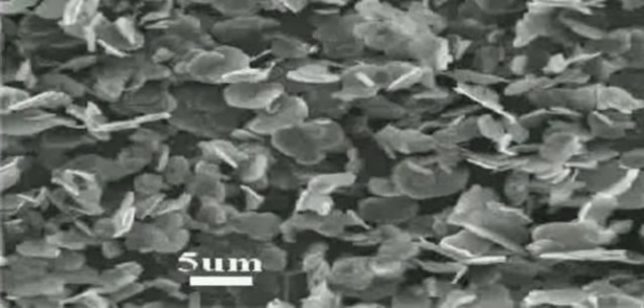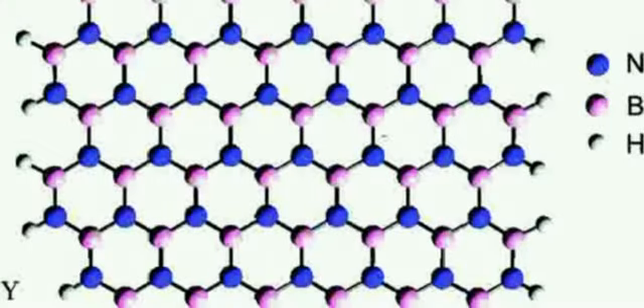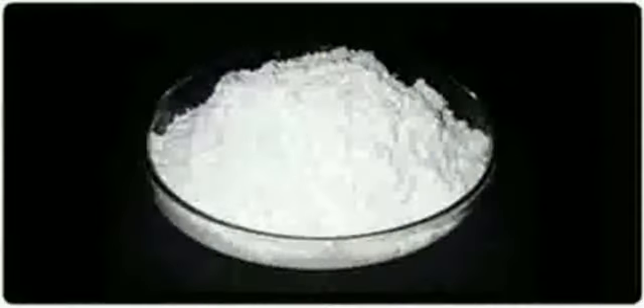Still, h-BN and graphite are very close neighbors, and even BC6N hybrids have been synthesized where carbon substitutes for some BN atoms. Hexagonal BN, h-BN, is the most widely used polymorph. It is a good lubricant at both low and high temperatures, up to 900 degrees Celsius, even in an oxidizing atmosphere. h-BN lubricant is particularly useful when the electrical conductivity or chemical reactivity of graphite, the alternative lubricant, would be problematic.